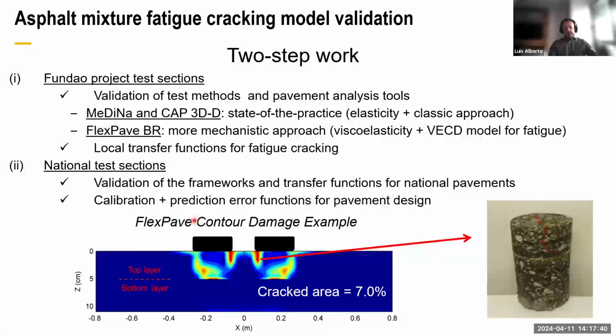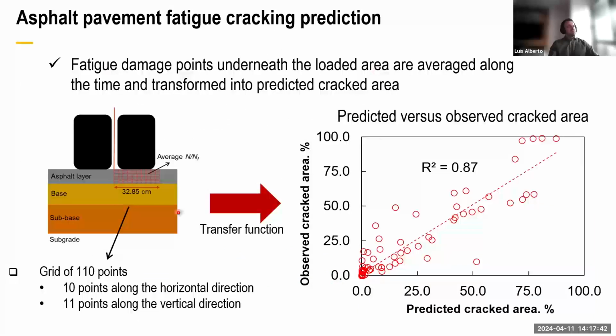And then we calibrated these functions. This is our first function calibrated for the fatigue cracking. We capture the damage underneath the load area. And from this area, we have a grid of damage points, and develop a transfer function to predict the cracked area in the pavement.